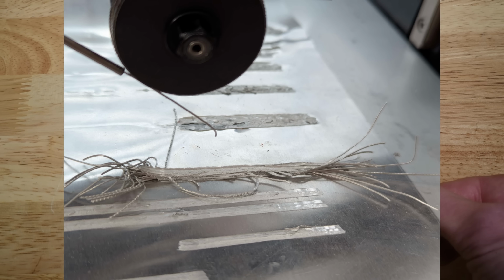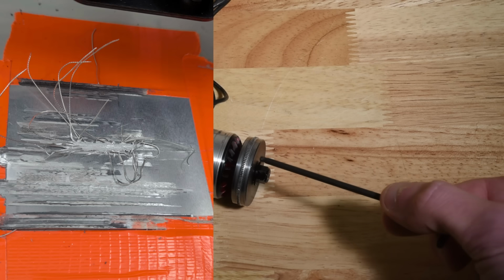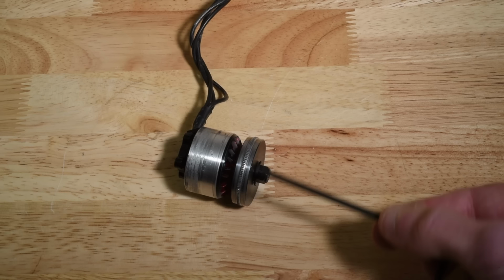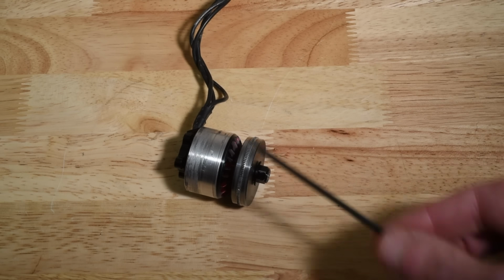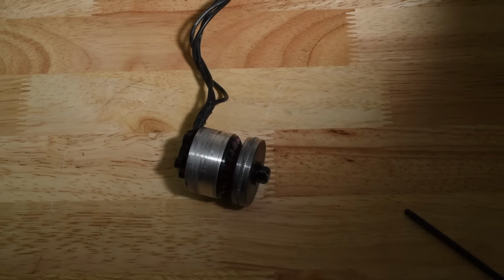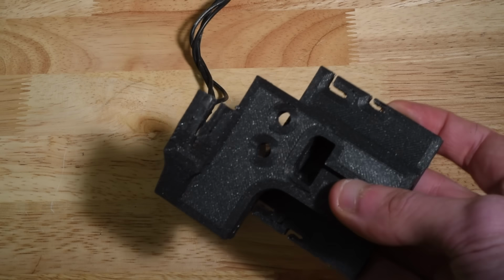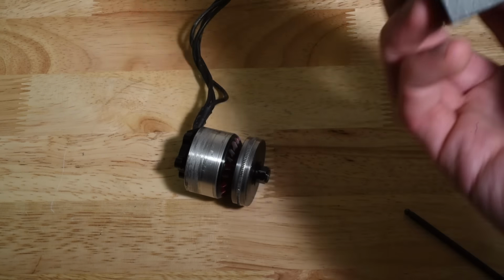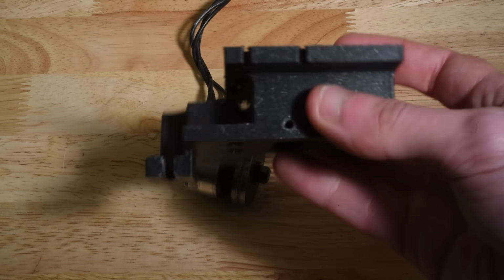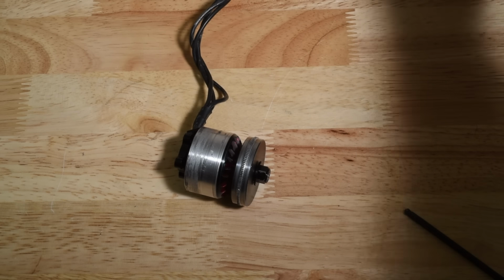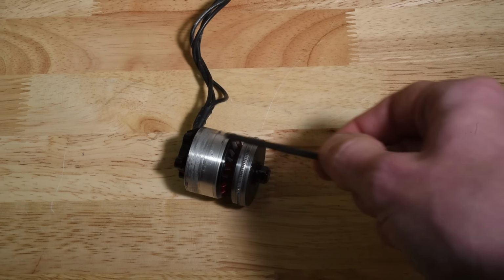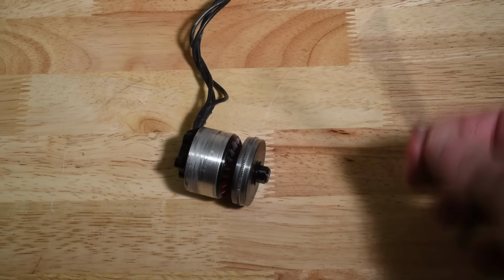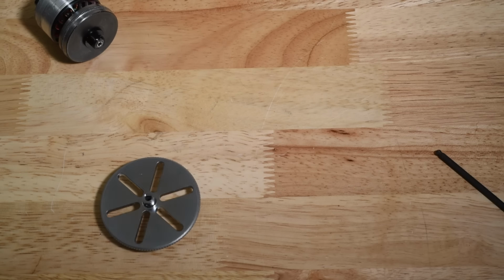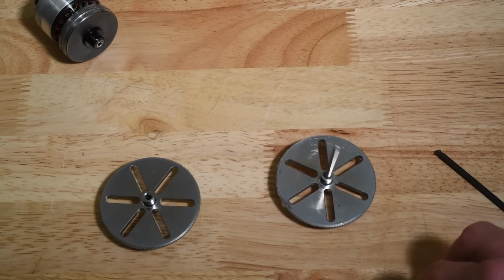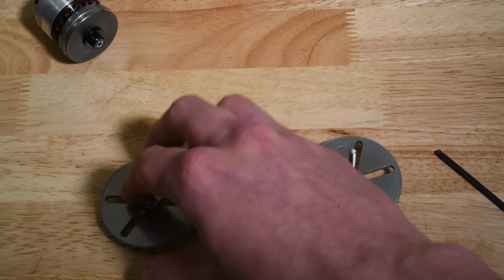So we decided to try and turn down the edges of the black oxide thumb nut to make it thinner and improve the resolution and improve the quality of the deposits. When we did that, we ran into a whole host of new problems, mostly having to do with the plastic wire guide and other elements of our system, the long, thin needle that we were trying to feed wire under the wheel with, as well as the tendency of the wheel to camber on the shaft of the motor. So, back to the drawing board. We started designing and ordering components from PCBWay to try and solve the problem.